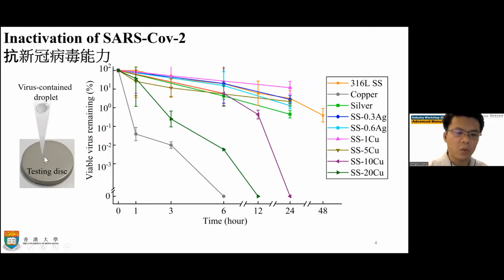So what you can see is we wait for a given period of time, from 1 hour to 48 hours, and then we measure the percentage of virus that is still viable, that means still live virus. The very beginning is 0 time. Look at this 316L stainless steel.